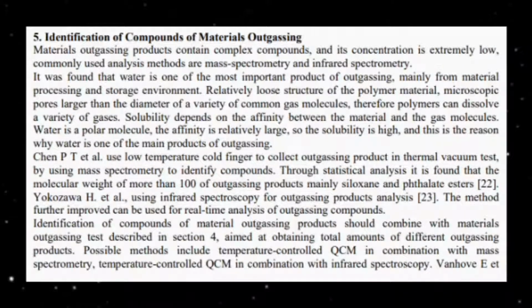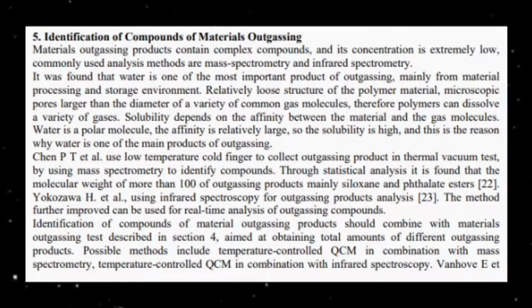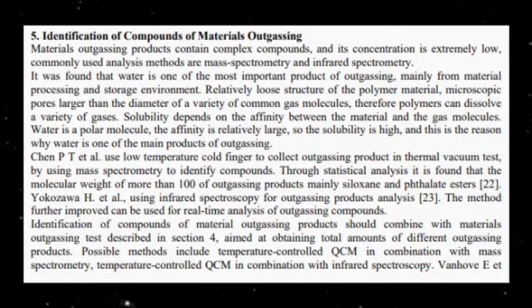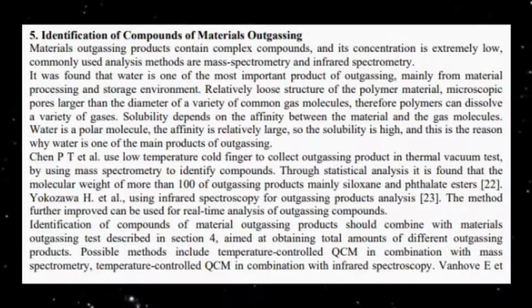5. Identification of compounds of material outgassing. Material outgassing products contain complex compounds, and their concentration is extremely low. Commonly used analysis methods are mass spectrometry and infrared spectrometry. It was found that water is one of the most important outgassing products, mainly from material processing and storage environments. In polymer materials with a relatively loose structure, microscopic pores are larger than the diameter of a variety of common gas molecules, therefore polymers can dissolve a variety of gases. Solubility depends on the affinity between the material and the gas molecules. Water is a polar molecule. The affinity is relatively large, so the solubility is high, and this is the reason why water is one of the main outgassing products.